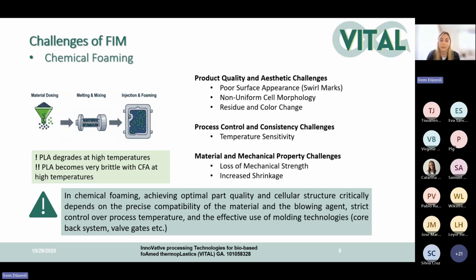There are also material and mechanical property challenges. Sometimes when we don't distribute the cells homogeneously in the parts, we can lose mechanical strength, and shrinkage can increase with chemical foaming. These are key points of the chemical foaming process. The chemical foaming agent amount is very critical for good quality parts, process optimization and process temperature are also critical, and mold suitability is critical too. Sometimes we need some mold technologies to make the foaming more efficient.